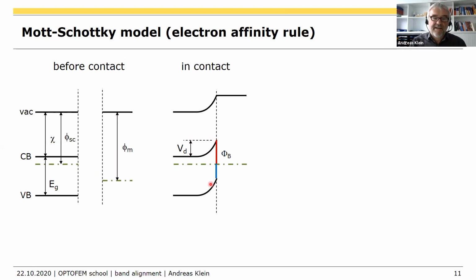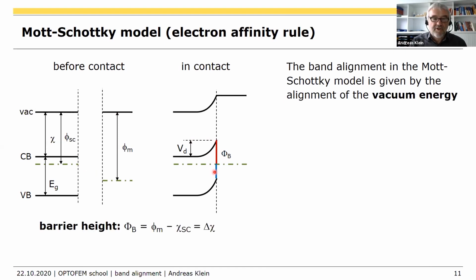And still we have the barrier heights, which are now determined by the difference in the electron affinity. So you see the work function of the metal and the electron affinity of the semiconductor. This is the electron affinity of the semiconductor. This is the work function of the metal. And the difference is the barrier height for the electrons. The band bending is the difference of the Fermi energies, and the difference of the Fermi energies is the difference of the work functions. So if you're talking about barrier heights, an important quantity for the Schottky barrier, you should talk about the difference in the electron affinities and not the difference of the work functions. That's a common mistake people are making.